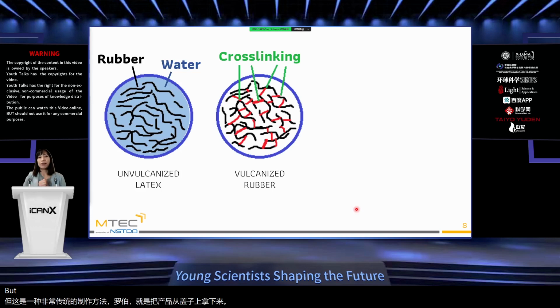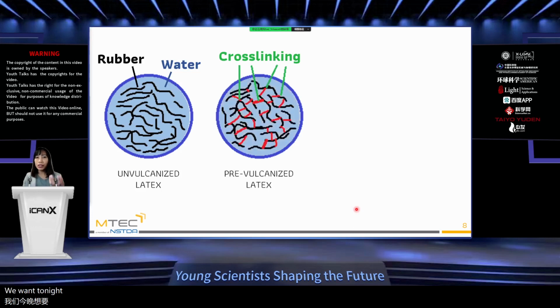But there's another way that we can do it. And actually, that was the way we made it printable. So instead of vulcanizing or cross-linking and removing water, we vulcanize, but we still keep the water inside. So right now you have the polymer that's already cross-linked, already vulcanized, but it is still floating like a colloid in water. So it's actually 50% water, 50% rubber.